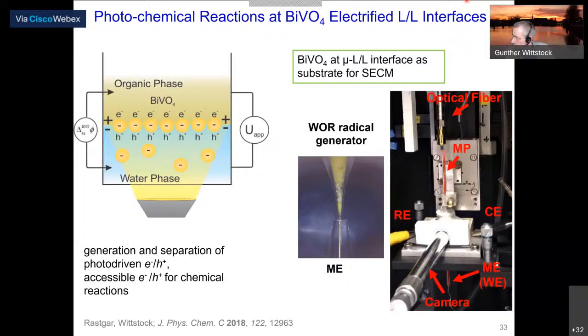So then you can take on that. Sai Kumar J. Naidu: any wide study carried out on stability of porous material at different conditions? Yeah, I mean, we did it not on a broad scale. We worked with nanoporous gold, and we did that intensively. And there were contradictory reports in the literature on the use of such materials in sensors and so on. Some reported coarsening, and others did not. First of all, there's a big role of the electrolyte. I think I made that clear in my presentation. If we go to alkaline electrolytes, we keep the residual silver at the surface, and that stabilizes the high energetic places on the surface, and that is actually quite stable.